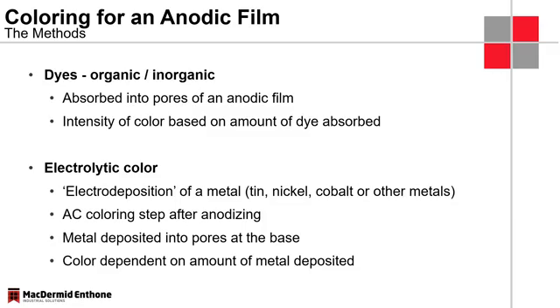And depending on how long we do this for and how many cycles we go through, the color we can achieve here is anything from a very light champagne to a dark bronze tone to the final color, which would be a very, very deep black color. Because this deposit really appears and is generated at the bottom of these pores, these colors have extremely good light fastness. They're very well locked in and therefore give extremely good performance.